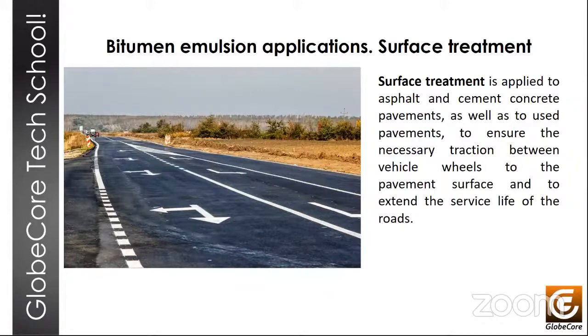Next thing is the surface treatment, and surface pavement treatment is performed on new asphalt concrete, on various types of black and cement concrete pavements, as well as on used pavements, to ensure the necessary traction of vehicle wheels to the pavement surface, and also to increase the service life of the pavement by protecting it against the elements. The layer created by surface treatment serves to give the coating certain roughness, water resistance, wear resistance, and certain density. And we're talking here about both an inexpensive one-time single treatment of secondary road surfaces, and also the creation of wear-resistant surface layers on roads with relatively high traffic density.